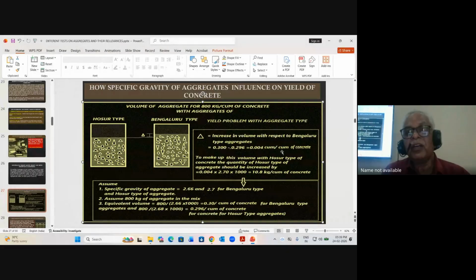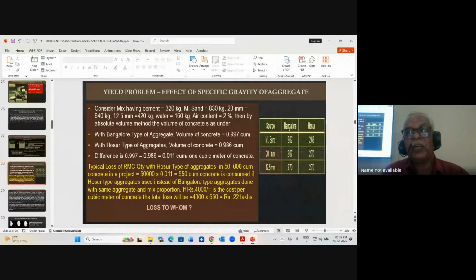It is only for coarse aggregate. I have made a study of a typical mix design, one with Bangalore source aggregate and one with Hosur aggregate, considering these specific criteria. In the concrete mix, total volume with Bangalore aggregate is 0.997 using the absolute volume method. Hosur type is 0.986. The difference is 0.011 cubic meter per 1 cubic meter of concrete.